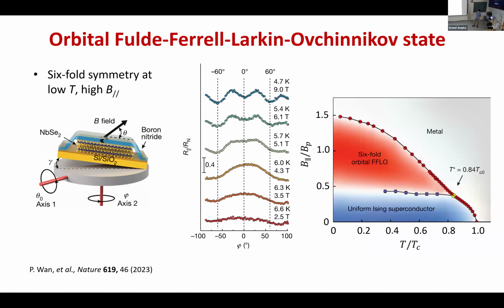And why is this related to the effect? Because they argue that, again, if you have FFLO state, you should be able to see an upturn, and they indeed observe this upturn. They also have some other effects, which are included in this paper. Now they also do a very careful two-axis rotation, so that from this experiment they observe some six-fold symmetry, which they claim is orbital FFLO state, and which is not the case when you are in this uniform Ising superconductor.